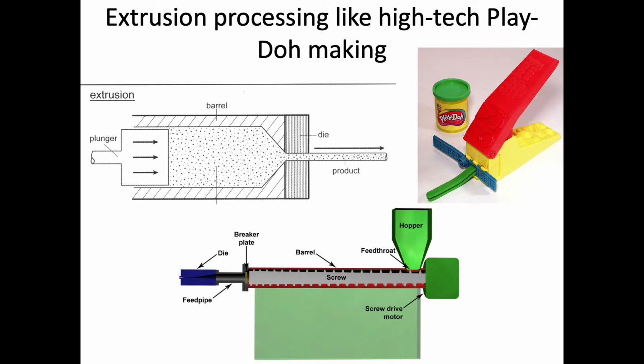All right. So another technique that can be used is extrusion. And so extrusion is pretty much like it sounds. We're extruding something through a die. And so in this case, we would have our ceramic in this chamber. We'd have a plunger to push it through this die of a given shape. And then that creates a certain shape. So I put this illustration of Play-Doh up there because that's pretty much what it is. You can see that the Play-Doh has different dies here, and you push it through that die to create a certain cross section, right? And so we can make whatever shape is limited to the die.